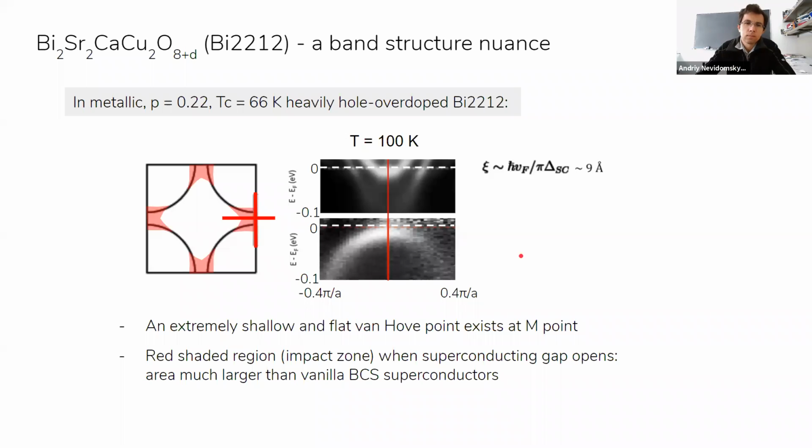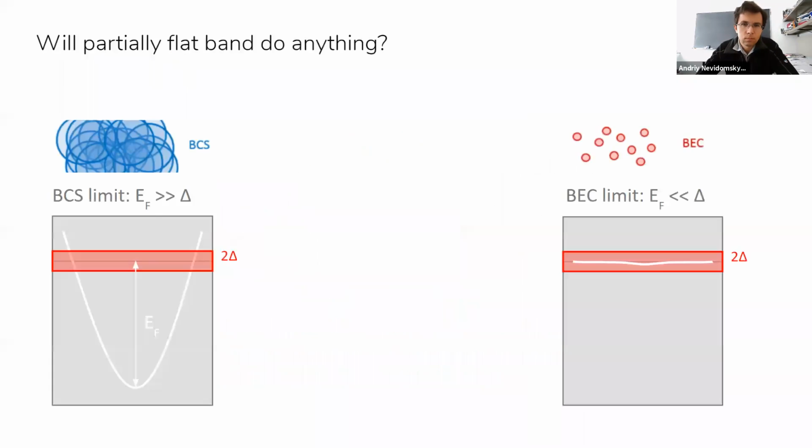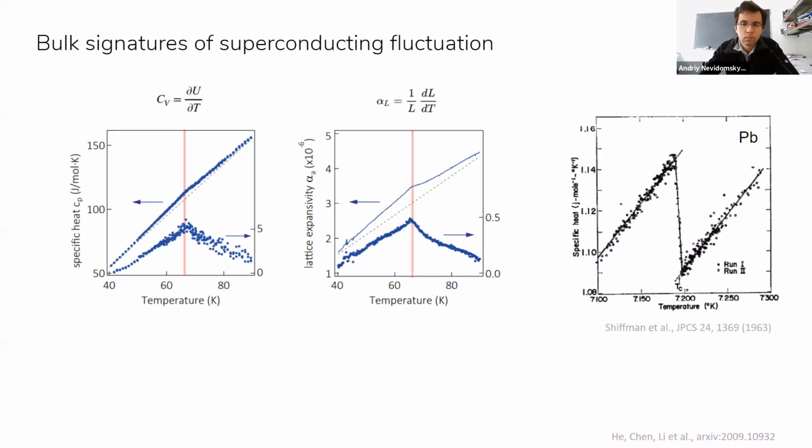Fantastic, thanks. So this unusual kink that you've seen, is that due to electron-phonon interaction or what? Not 1 millivolt. It's about 100 millivolt. Yeah, 0.1 eV. So I don't think that's a result of electron-phonon coupling because the highest energy phonon in cuprate is about 80 millielectron volt. That's right. It also cannot be due to magnetism, right? I mean, there's no spectral weight, just like you're saying, right?